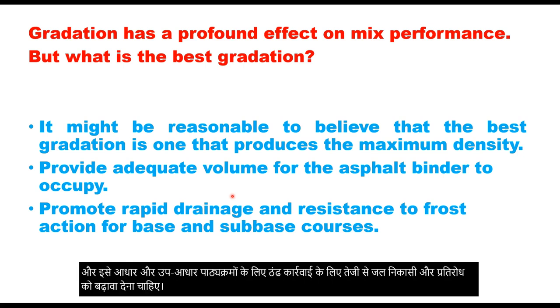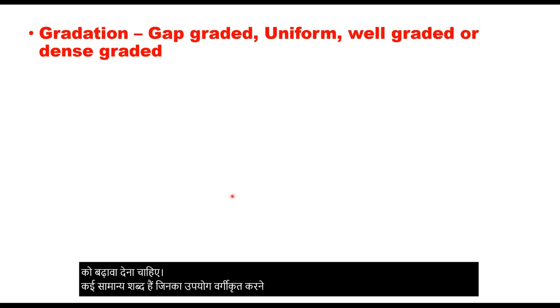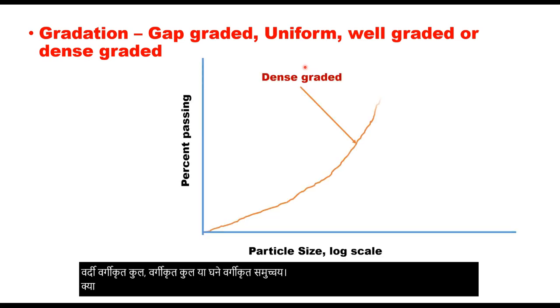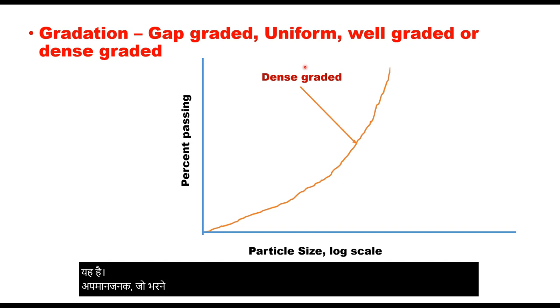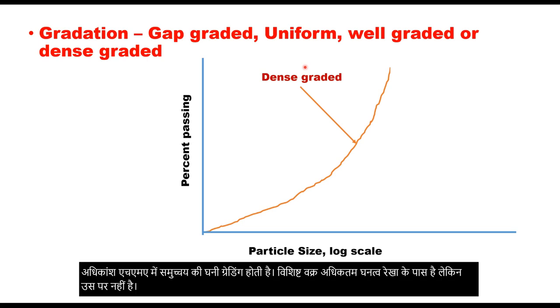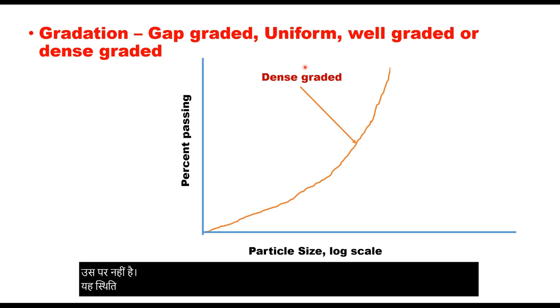There are several common terms used to classify gradation: gap graded, uniform graded aggregate, well graded aggregate, or dense graded aggregate. In the case of dense graded aggregate, it is the grading which is very close to Fuller's curve, or the maximum density line curve. Most HMA mixes have dense grading of aggregates. A typical curve is near the maximum density line but not on it. This gradation gives low void content, low permeability, high stability, but it is difficult to compact.